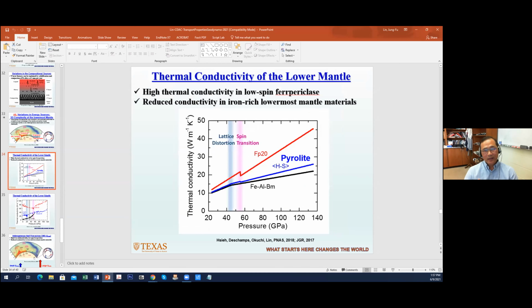So for the iron alloys, the major mechanism is the electron-phonon scattering, right? The electrons scatter off the lattice. But in the silicates and oxides, such as ferropericlase and bridgmanite, the dominant conductivity mechanism is phonon scattering. Does that answer your question? So the radiation thermal conductivity. So that's the lattice thermal conductivity, right? And so that's what we measure. Lattice thermal conductivity.